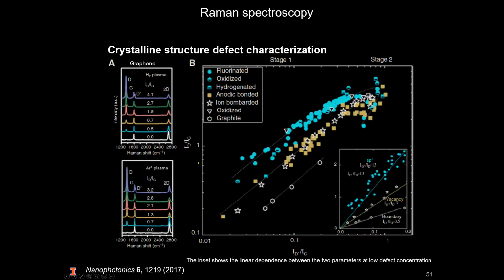This work presents a systematic study for different types of defects in graphene, and shows how those defects affect the graphene Raman spectrum. In the inset here, we can see different types of defect will present a different evolution of the Raman peaks, in this case, the D over D prime intensity ratio.